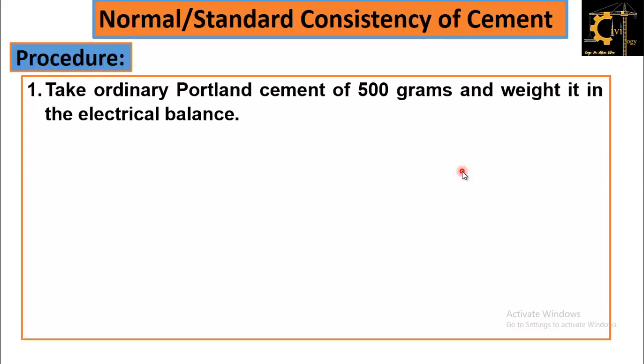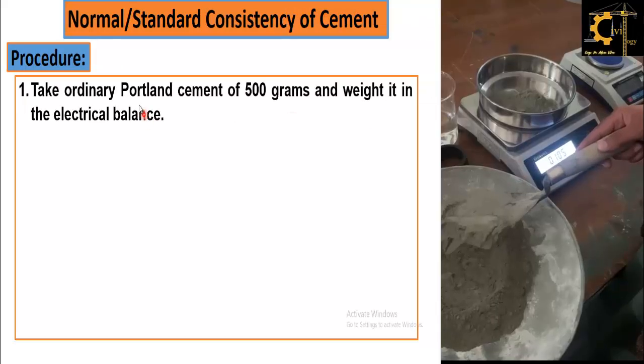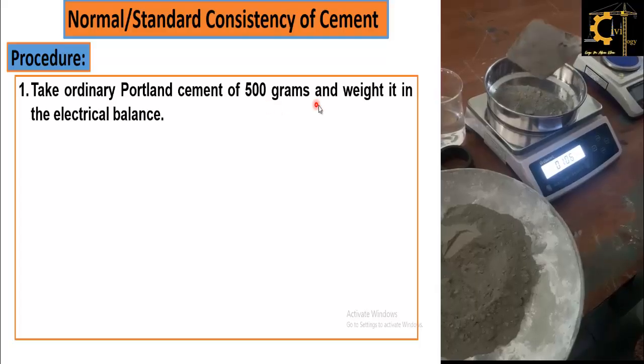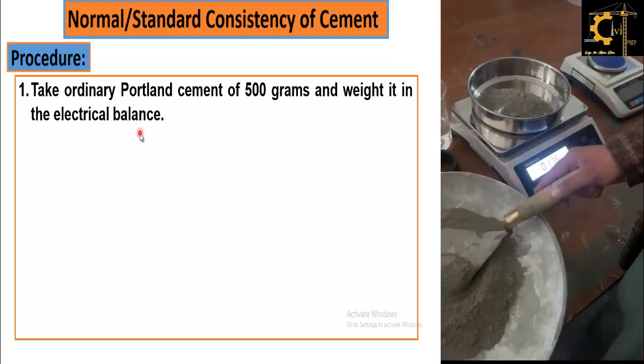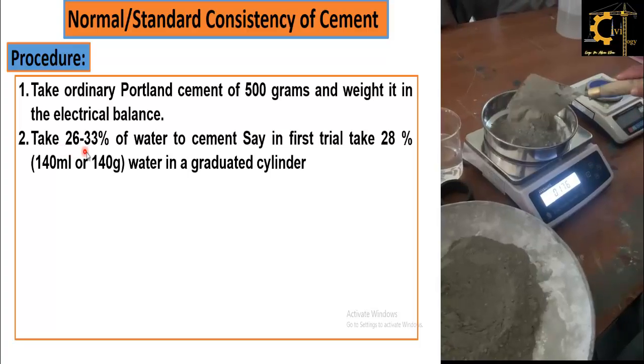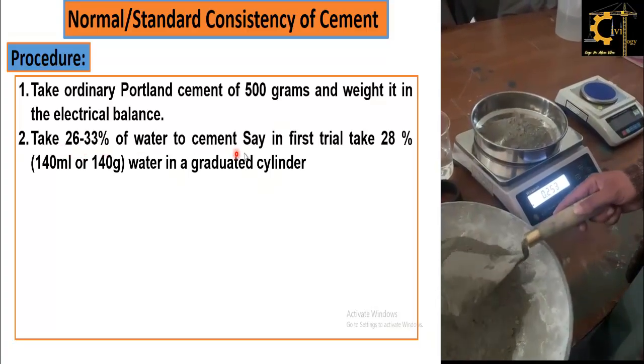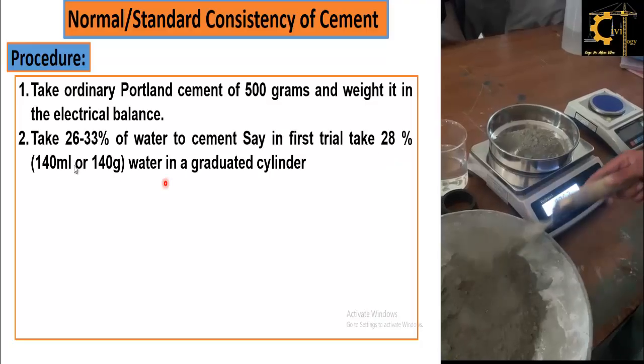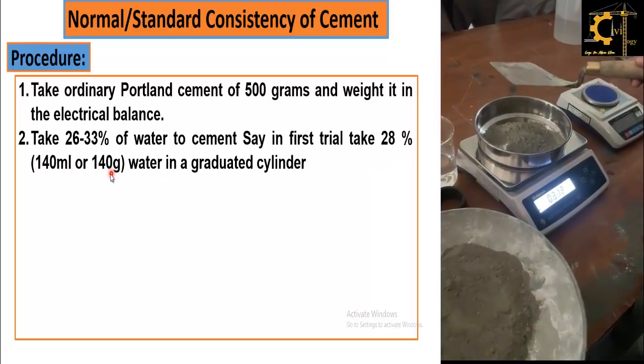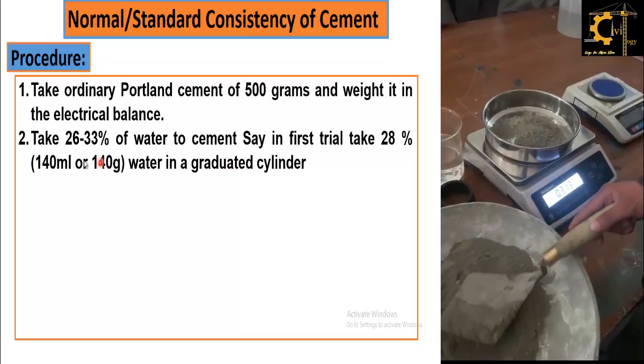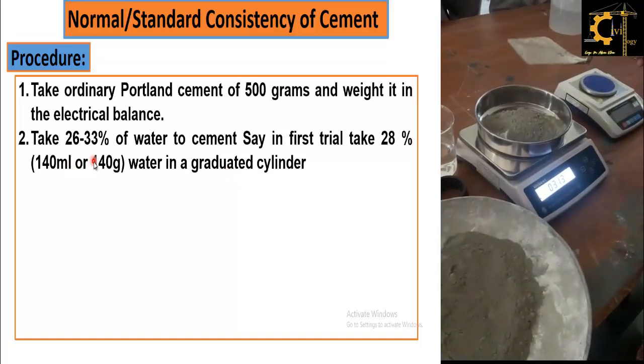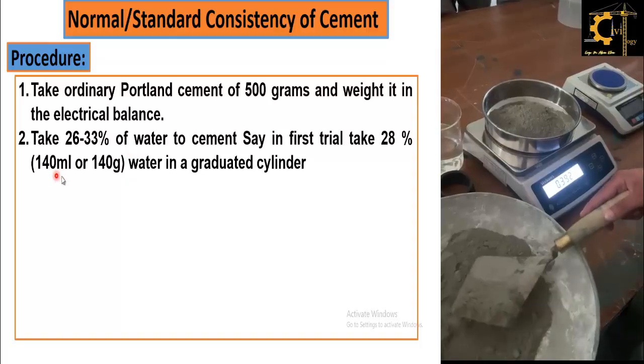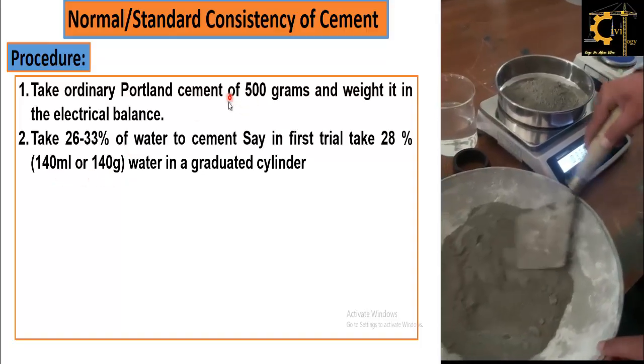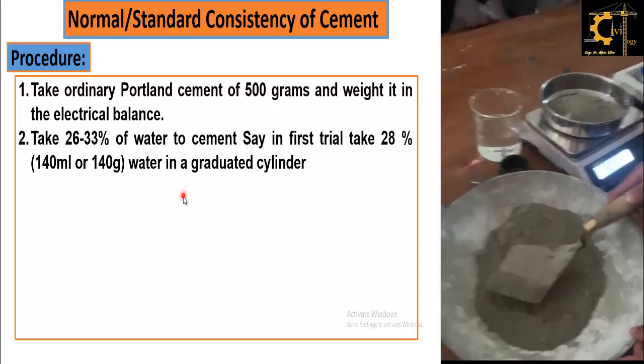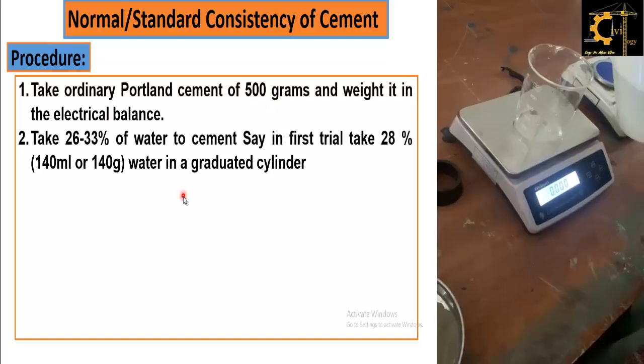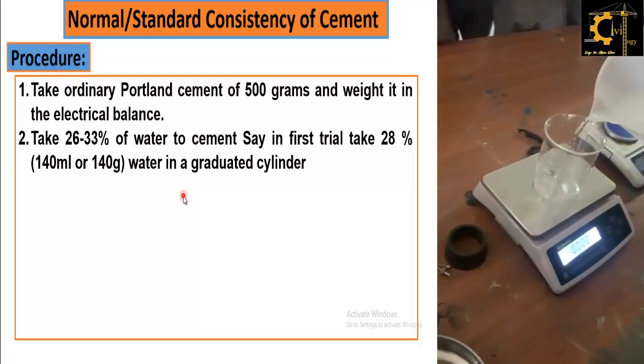Now coming towards the procedure, the first step is to take ordinary Portland cement of 500 grams and weigh it in the electrical or physical balance, and take 26 to 33% of water to cement. Say in the first trial take 28%, that is 140 gram water, in a graduated cylinder. If we take 28% of 500 gram of cement, it will come out to 140 gram.